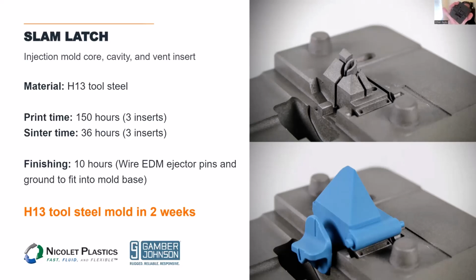They had to insert this as well, but they printed all 3 of those in about 150 hours, so about 7 days here. All 3 of them went in the furnace at the same time for about 36 hours. They only needed to do about 10 hours of finishing work here. They did some wire EDM just on those ejector pins. You can see we're able to print those ejector starting holes in. I don't know how well it comes across on my camera, but there's some really small holes in here that you print in a starter hole, then they just wire them out just because of how precise those need to be. And then they did a little bit of grinding to fit this into the mold base.